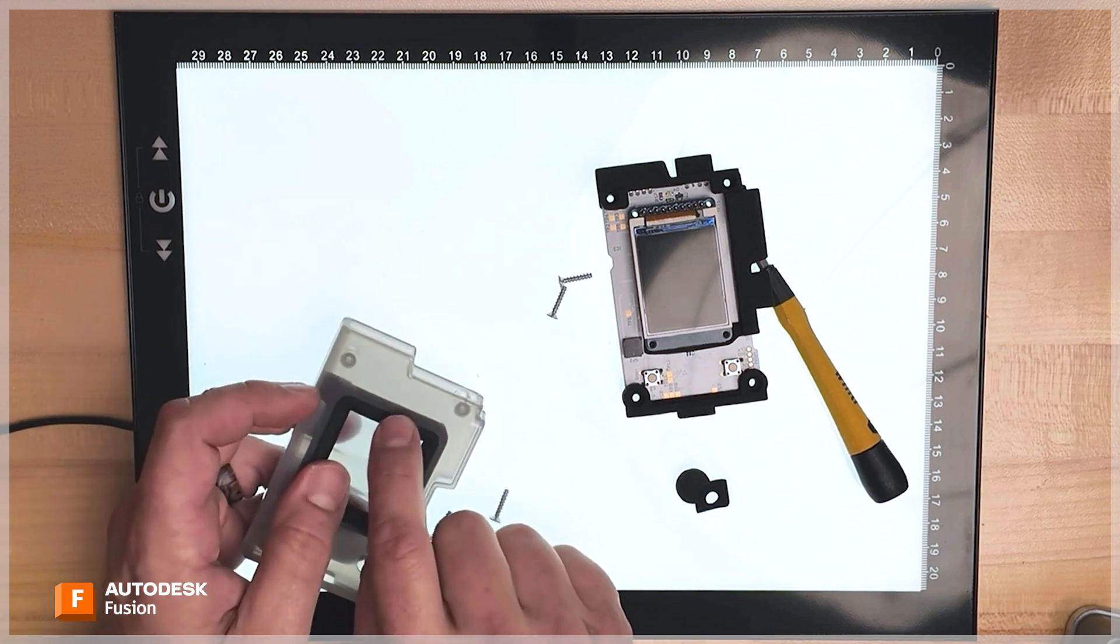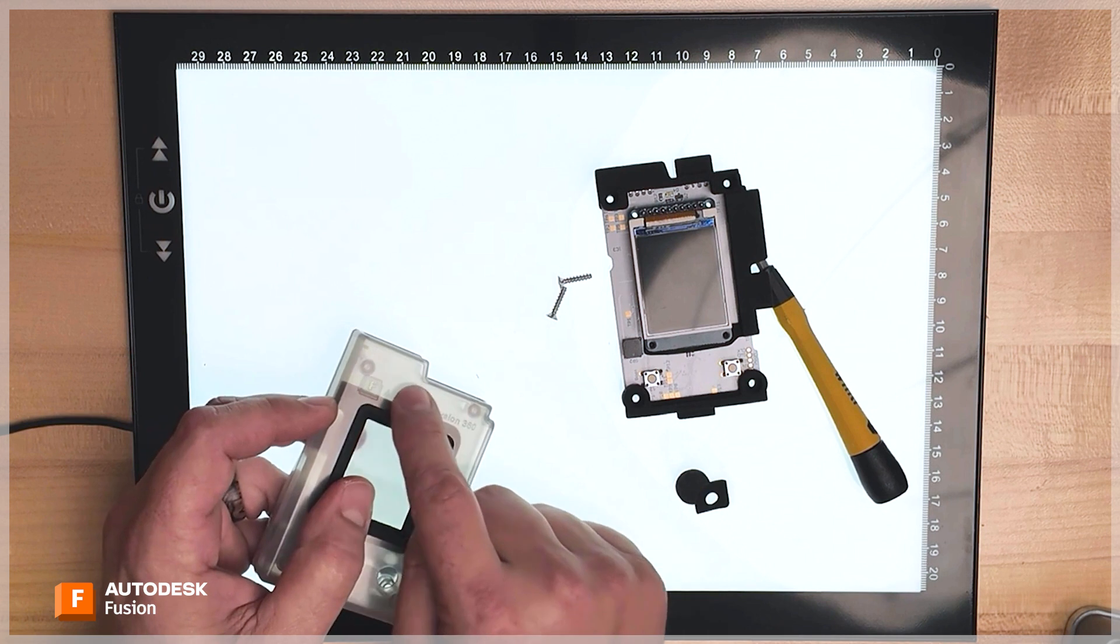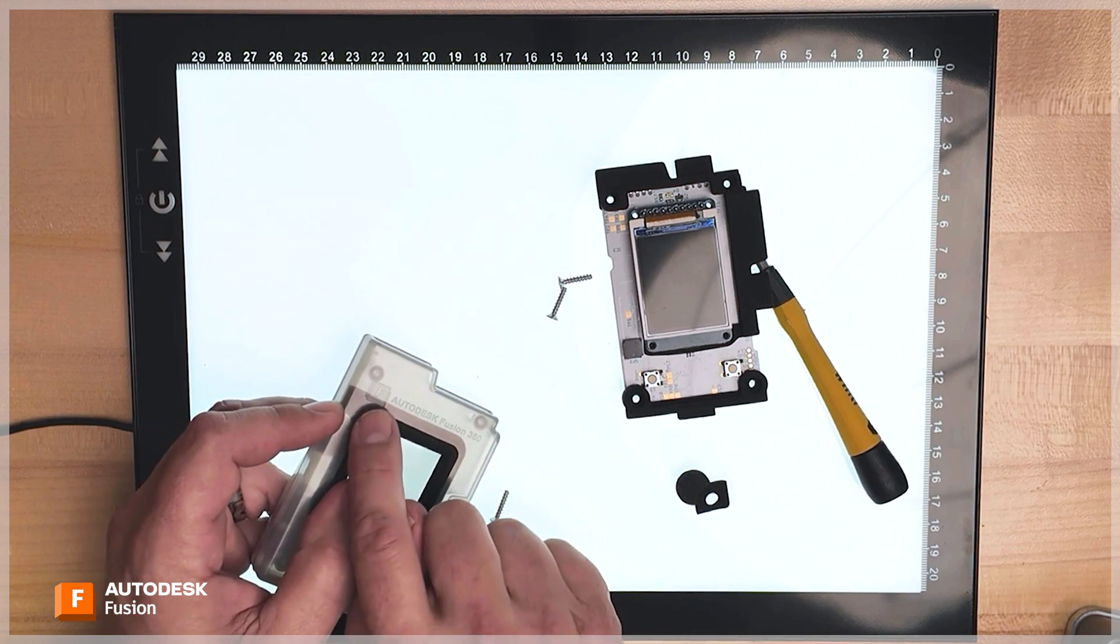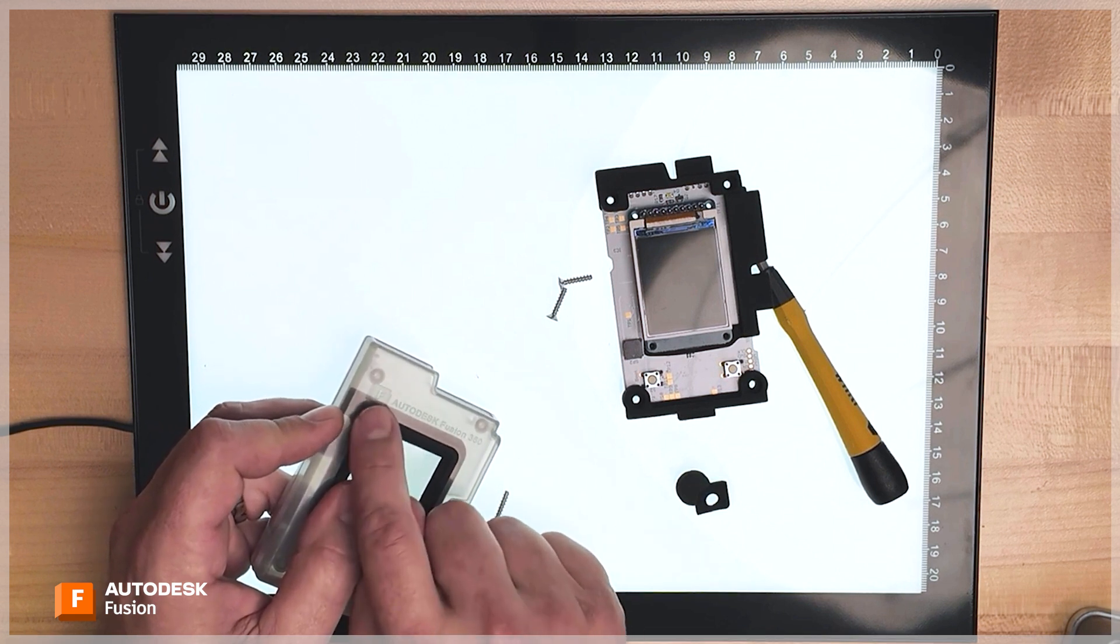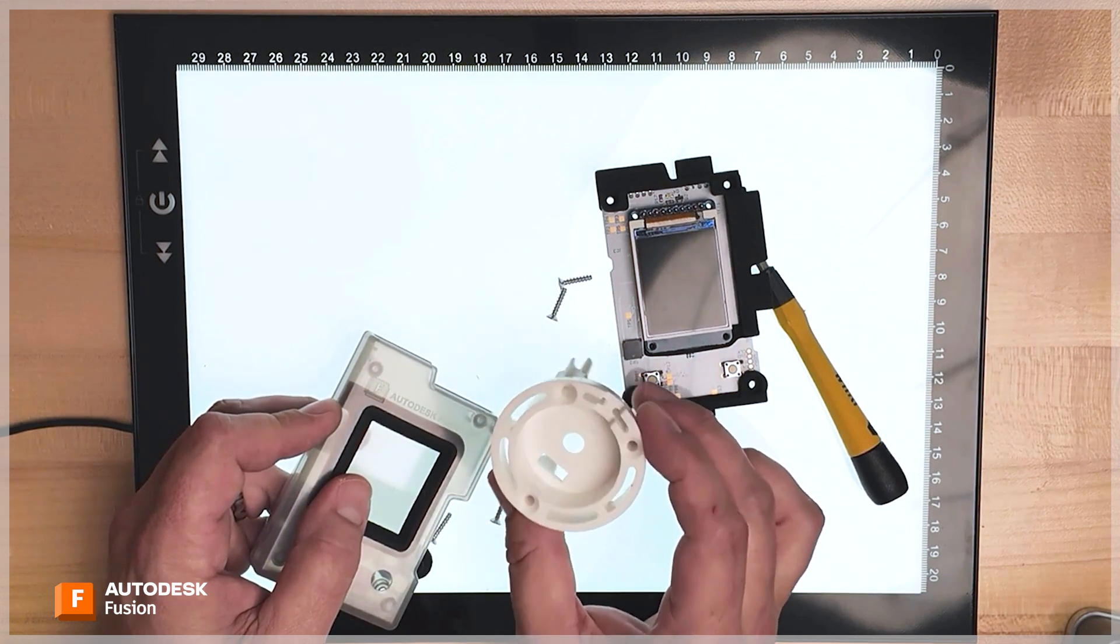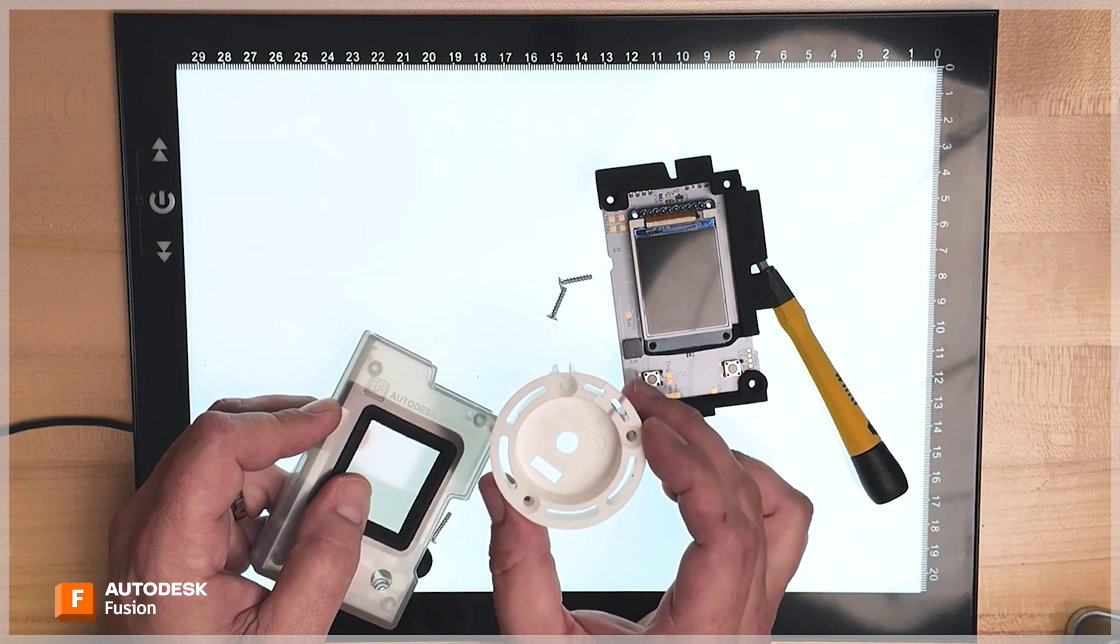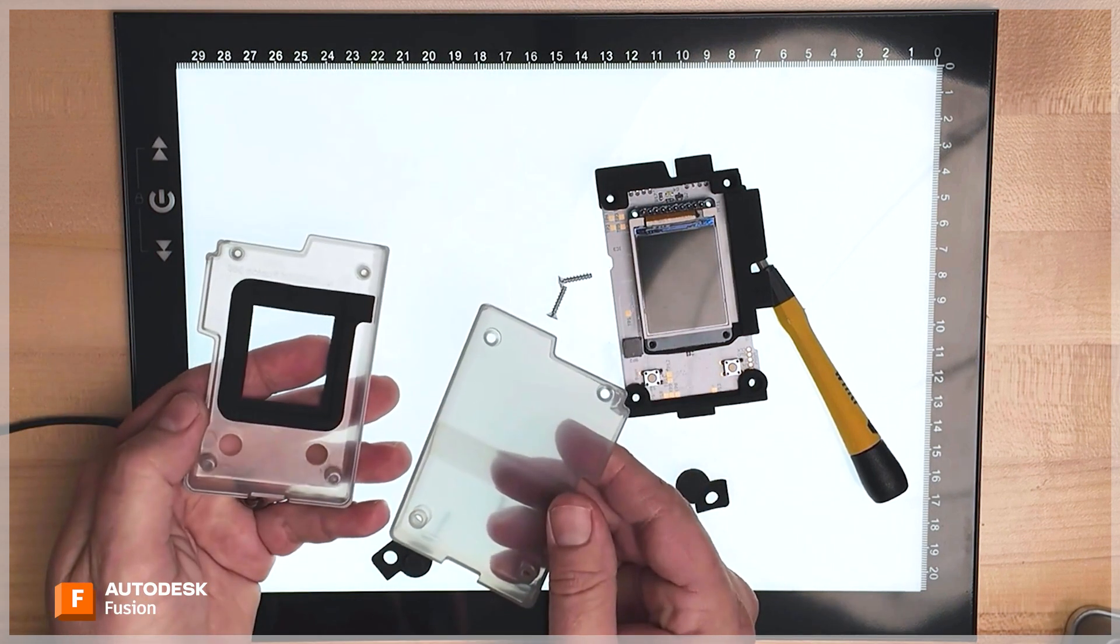This is another one of those places where you can see thicknesses and plastic rules coming into play. Because if you didn't have the depth of this hole just right, you would get sinking on there. It would either sink from being too much plastic or from being too little. One thing that's fun about this product is the emboss logo on there. This one is embossed up, and that means it is not steel safe. So when I went to the brand people, they didn't want us to use this little F logo because they thought that should be in color. And I had to tell them, unfortunately, we couldn't take that off. Because again, this is positive, meaning it's negative in the mold. Whereas this older one, we did it the right way, where it was negative on the part itself, meaning it would be positive on the mold, in which case you could mill it down later without making a whole new mold. So steel safe, you got to think about that when you're making this stuff.